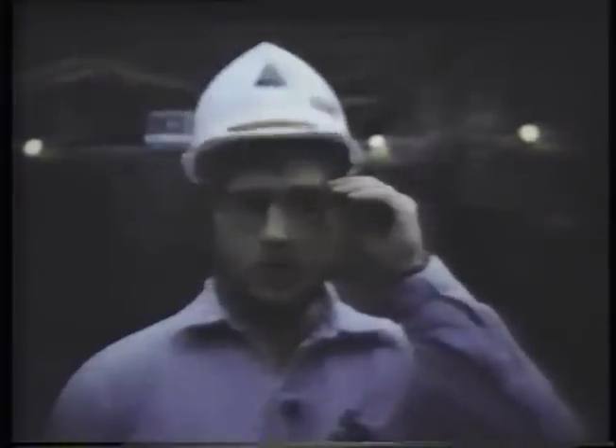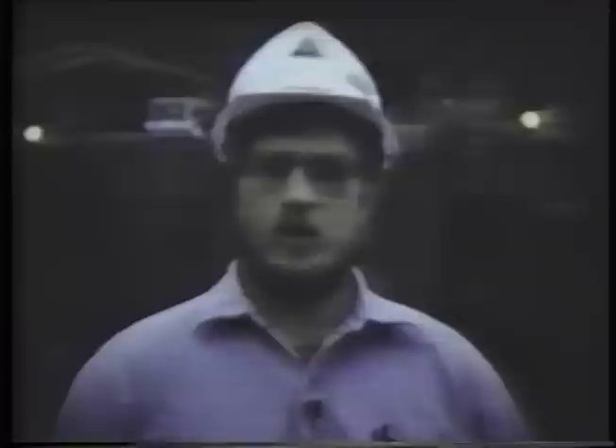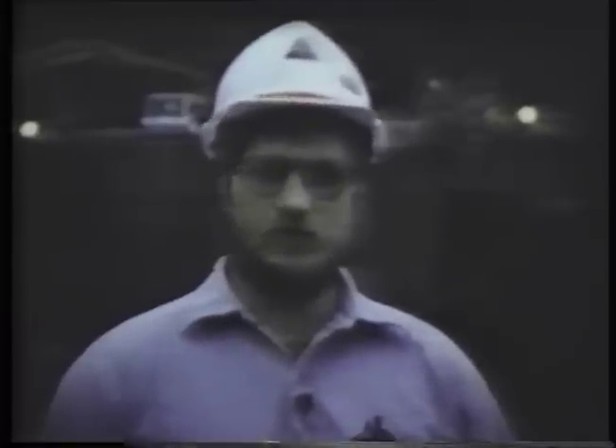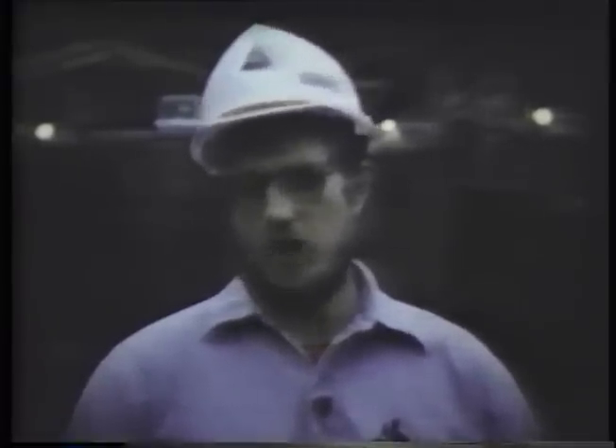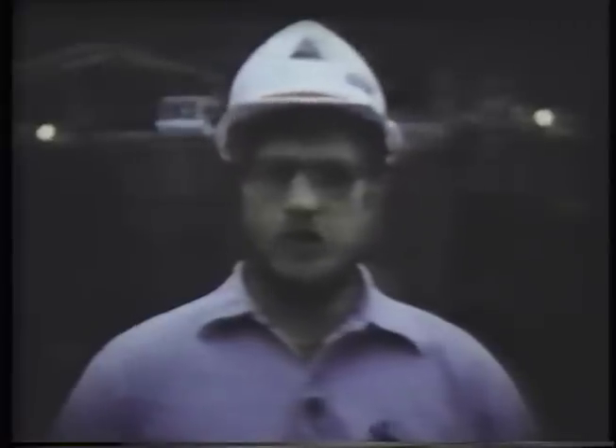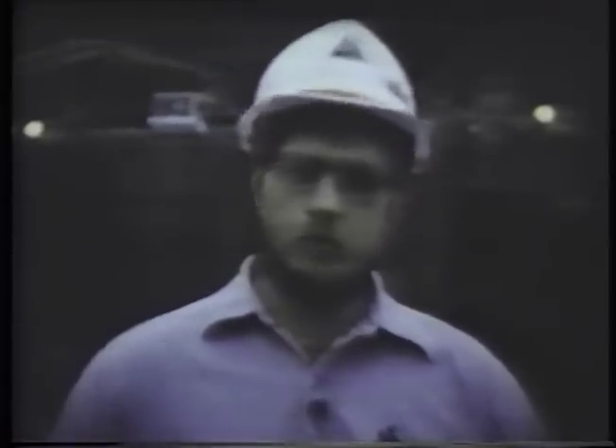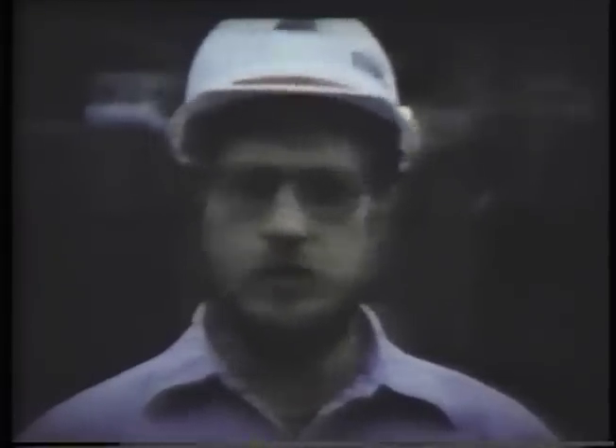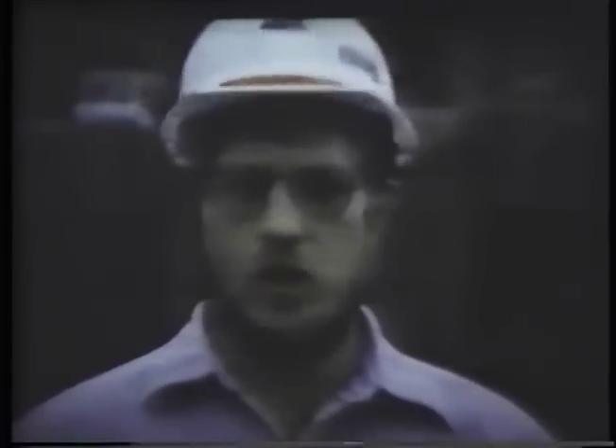I can't think of anywhere else in the United States today where they're pumping 10-inch concrete and getting 16,000 psi unconfined compression test results in 28 days. That's what we're doing here. That's one sample we have received. The average is closer to 13,000 psi in 28 days. But you have to keep in mind, this is flowing concrete. Typically, it's a 10-inch slump.